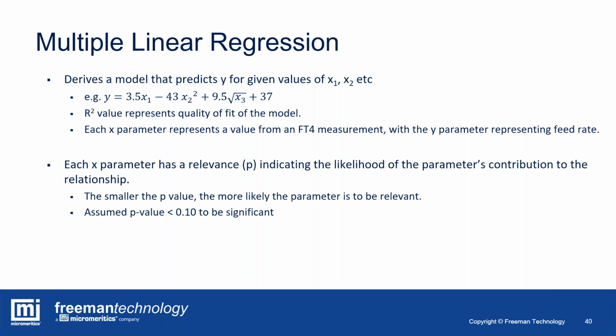We used a relevance parameter P to indicate the likelihood of that parameter's contribution to the relationship. The smaller that value, the more likely the parameter is to be relevant. Anything greater than 0.1 we considered to be insignificant, so parameters that gave us p-values of less than 0.1 were considered in the model.